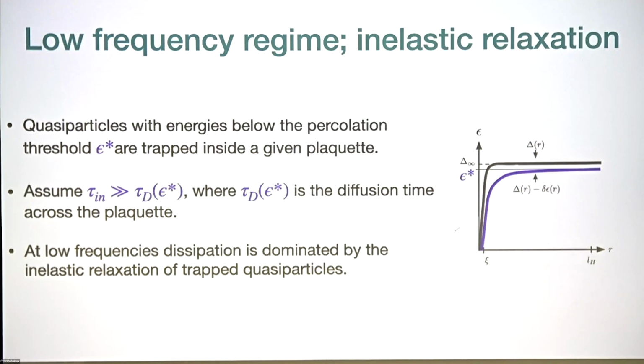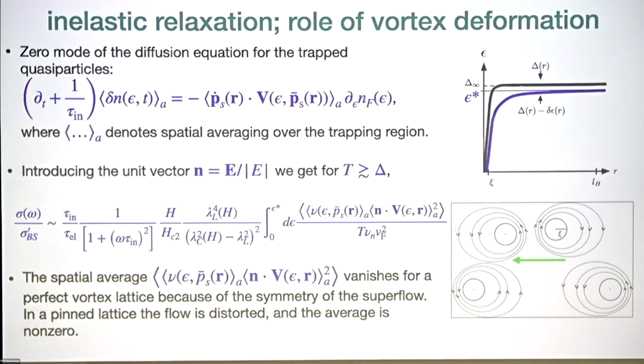So then I will assume that the inelastic time is longer than the diffusion time across this vortex plaquette. And therefore, at lowest frequencies, diffusion stops, and the dissipation is dominated by the longest time scale. To get this inelastic contribution, we consider the zero mode of the diffusion equation, and then relaxation occurs via inelastic collisions only. And the generation of this zero mode is proportional to this averaged over the plaquette product of condensate acceleration by the vortex sensitivity.